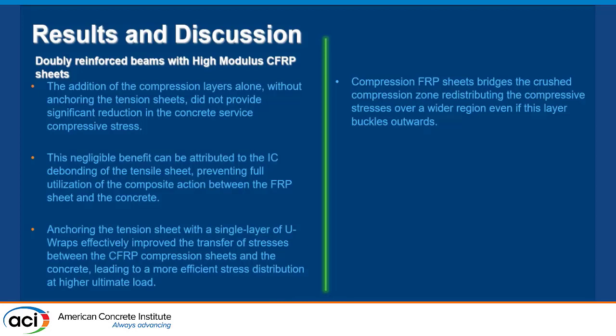So mainly the compression FRP sheet bridges the crushed compression zone and redistributes the compressive stress over a wider region, even if this layer buckles outward. So the addition of the compression layer alone without any anchoring did not provide a significant reduction in the concrete surface stress. The negligible benefit can be attributed to the intermediate crack debonding of the tensile sheet, preventing the full utilization of the compressive behavior. So the solution was anchoring the tension sheet with a single layer of U-wrap, which effectively improved the transfer of stresses between the FRP compression sheet and the concrete, leading to a more efficient stress redistribution at a higher ultimate load.